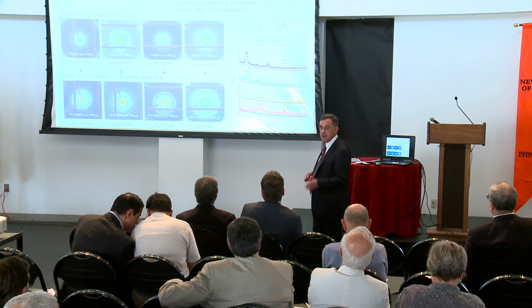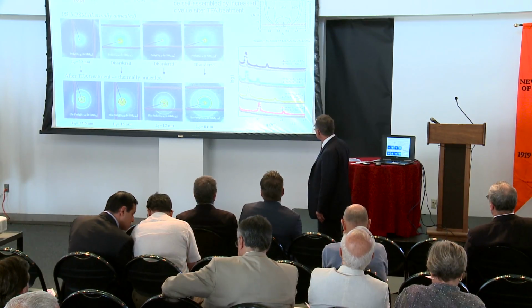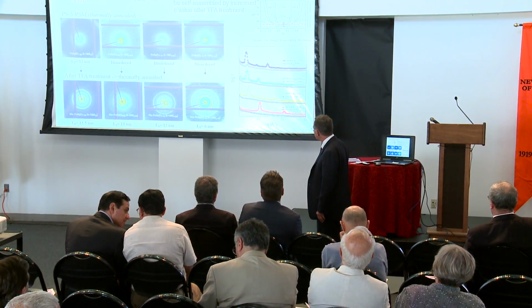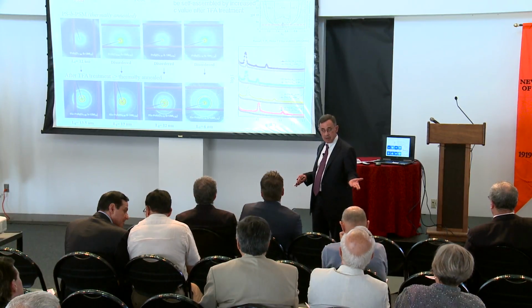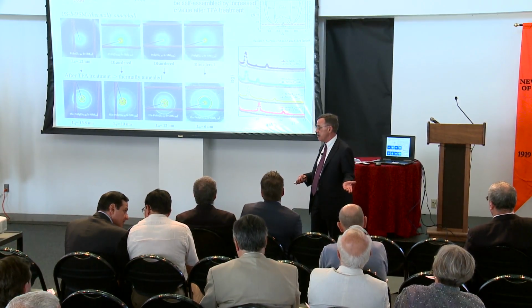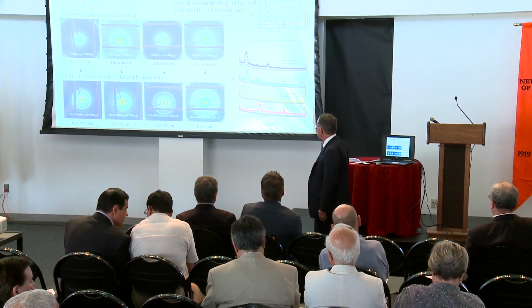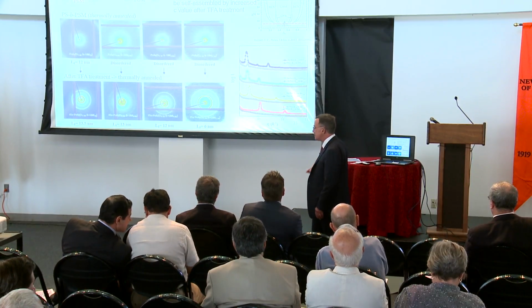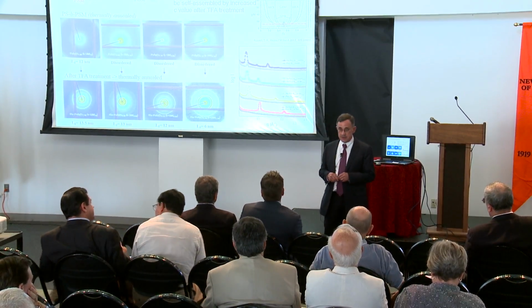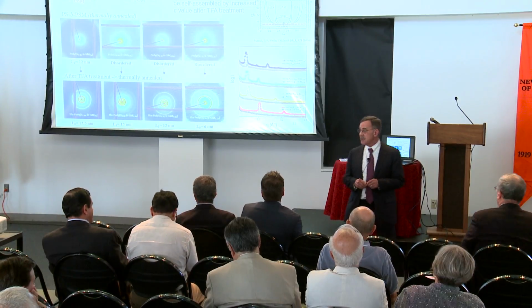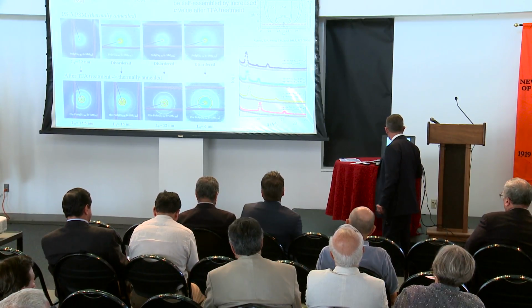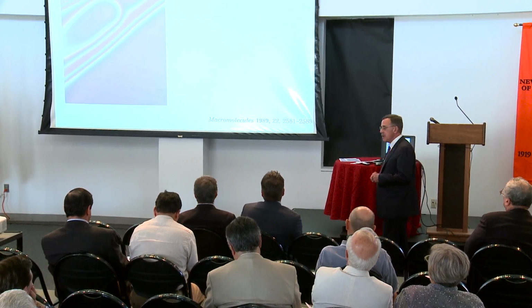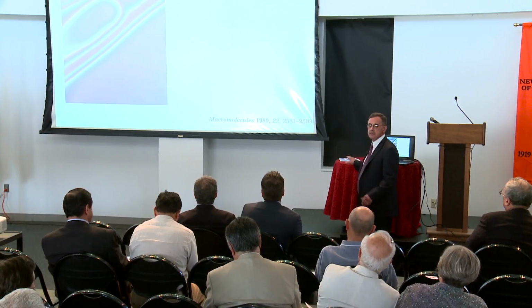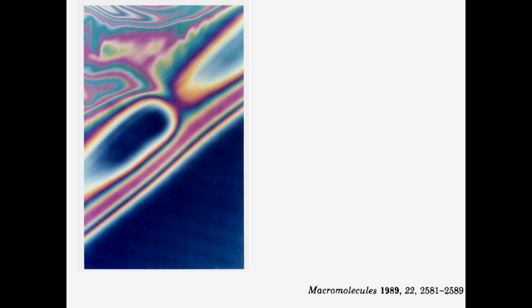Just by doing this chemical magic or trick, I start off initially with scattering profiles that are very diffuse, and that's characteristic of a phase-mixed copolymer. Expose it to the trifluoroacetic acid, and I now start to develop these sharp reflections. And that tells me I've gone from the disordered state into the ordered state. Now, even you could answer this question.